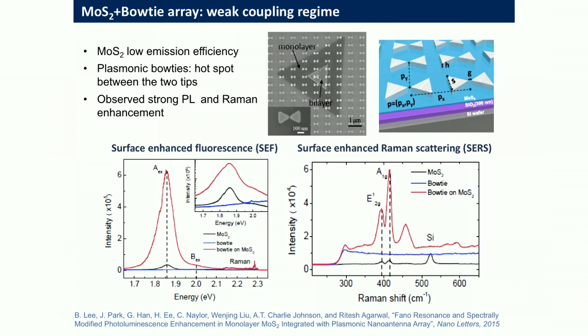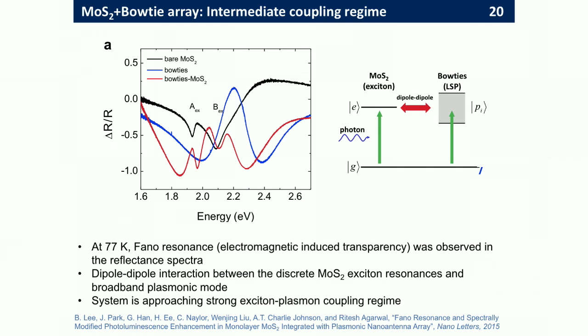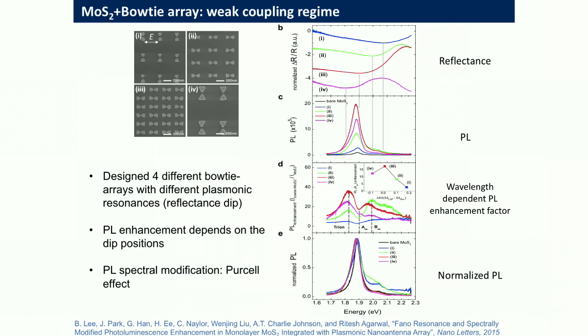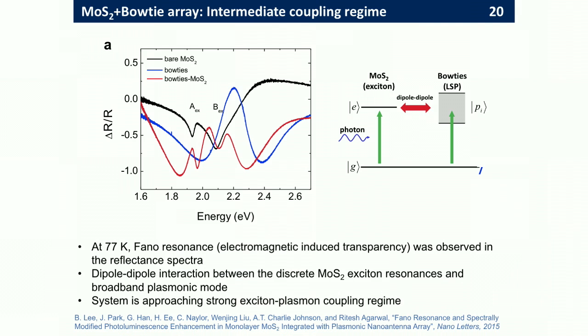As I said, the quantum yield of this material is less than 1%. It's like 0.01% or 0.05%. So we showed 100 times enhancement in the emission and also Raman enhancement by engineering these cavities. So we can get very large Purcell factors, and then just by changing the geometrical parameters, that is the size of these triangles and the spacing between them, we can get resonances at different spectral locations and tune the optical emission spectrum of these devices.